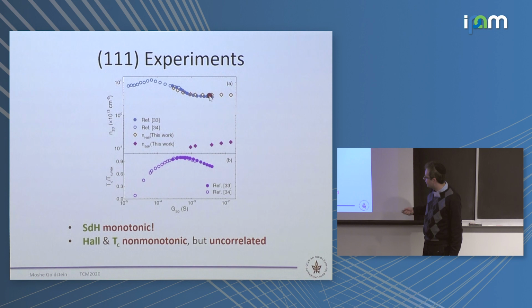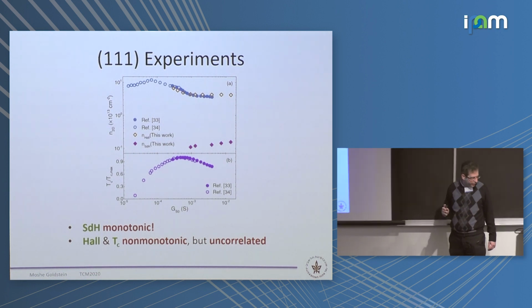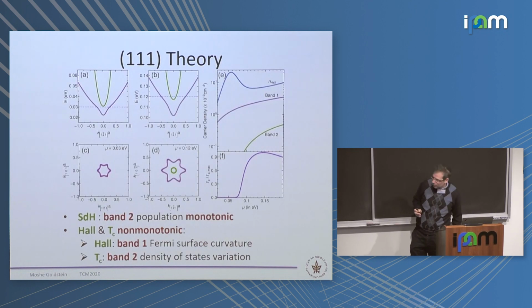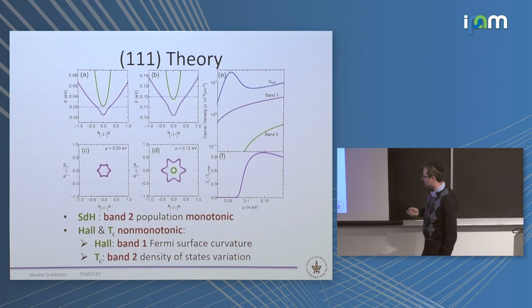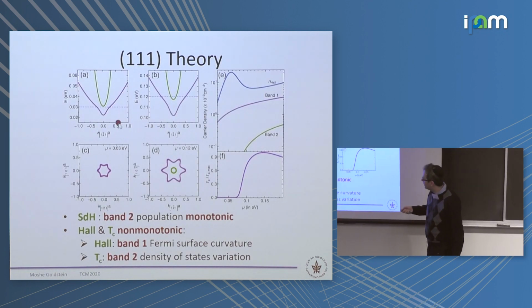It's a very different scale. When you look at TC, it also has a peak. The peak in TC is very far removed from the peak in Hall. So they both have peaks, but they are not correlated as used to be the case in 100. So this is different. And when we come to the theory, all those things are very natural, because when we look at the bands, now the bands have quite similar masses. They are different, but not very different.